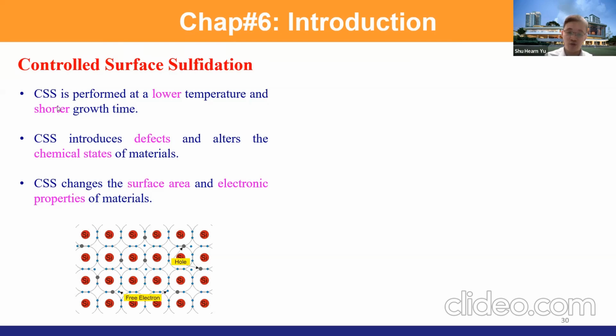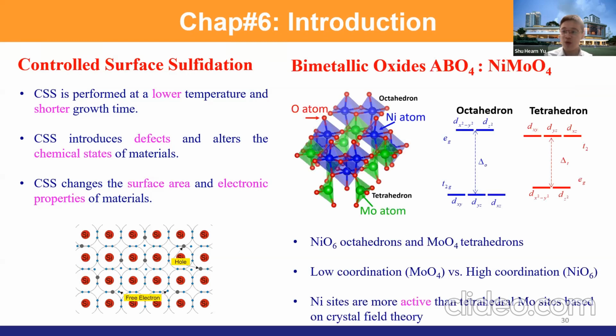I don't want to do full sulfurization. I perform at lower temperature and a shorter time. So the controlled surface sulfurization can introduce some defects, and it also can introduce some new chemical states. These are not very explored by many people. This is a relatively new field. And this is what we have.